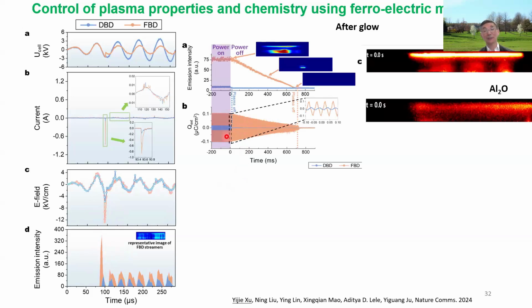And more interestingly, it dramatically increases afterglow. If we turn off the plasma, for alumina oxides, the plasma basically stops. But with ferroelectric, because of the polarization of the surface, you can see that the oscillation of the charge gives you hundreds of milliseconds of afterglow still there. You can see this thing. That creates a great opportunity. You can generate hybrid plasma using the nanosecond to control the breakdown, and use afterglow to control vibrational excitation for chemical synthesis.